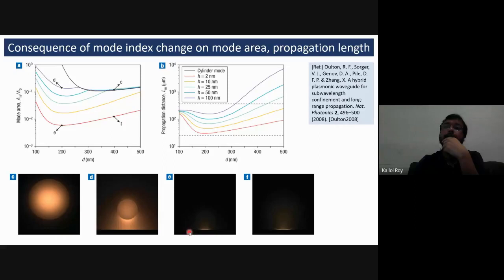Although the light is getting confined at the metal dielectric interface, there is a loss that comes with it, and because of that you can see the propagation loss is high. For example, if we take a particular d, say 500 nanometers, and compare different gap sizes, say a 100 nanometer gap versus a 2 nanometer gap, you can see that the propagation length is very different. It changes by almost 2 orders of magnitude.